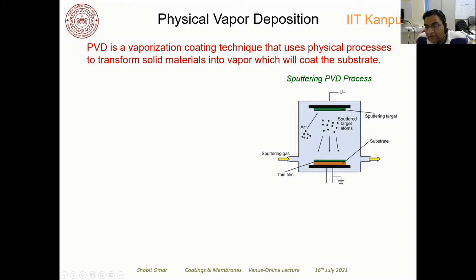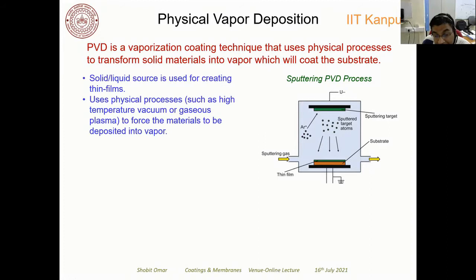This figure shows the sputtering PVD process. You can see that on the top you have a target, and the sputtering gas is fed into this chamber, which has a high vacuum, and this sputtering gas sputters the target, and the atoms are ejected out from this target, and these atoms in the gaseous or vapor form get deposited on the substrate. Okay, so this is normally the principle of physical vapor deposition. Here I just showed you the sputtering PVD process, which I will discuss later also. But the important aspect of PVD is that you can use a solid or liquid source to create thin films, right?